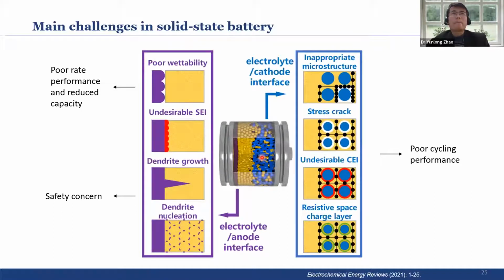So actually, there are still a lot of challenges in solid state batteries. This is why they haven't been commercialized. Especially, you can imagine if we are using all solid state electrolytes, the main challenge will be generated at the interface, at the electrolyte and anode interface, or the solid electrolyte and cathode interface. For example, if it is a solid interface, it can have very poor stability between your anode and the electrolyte. Also, if there is a very good SEI, it can protect the materials and give very good cycling performance.